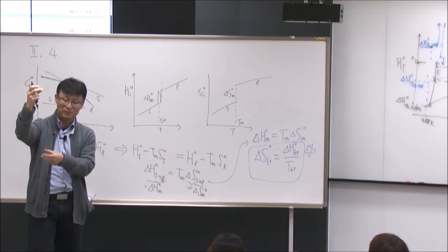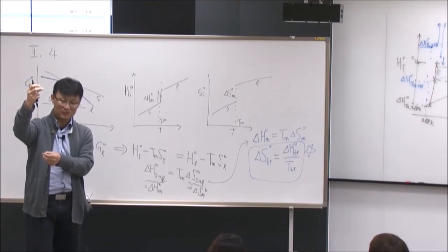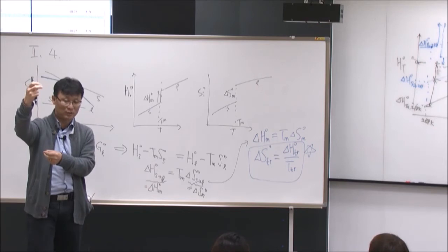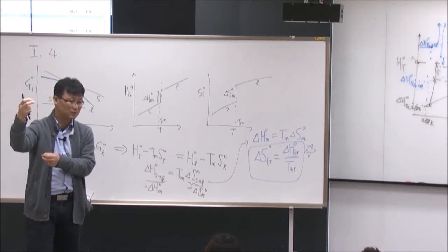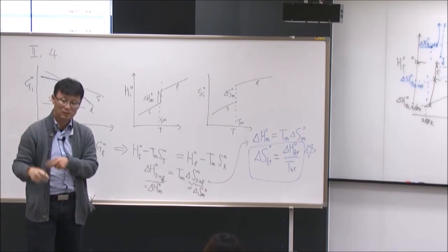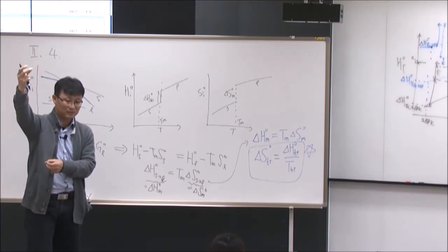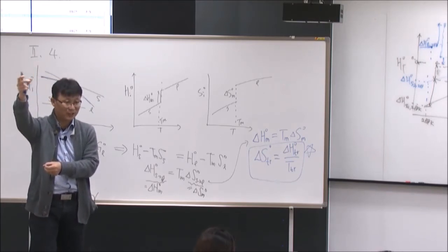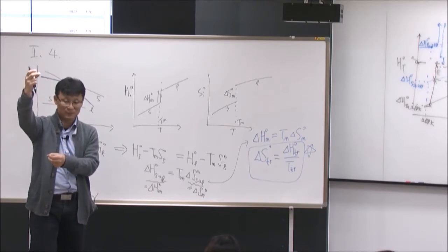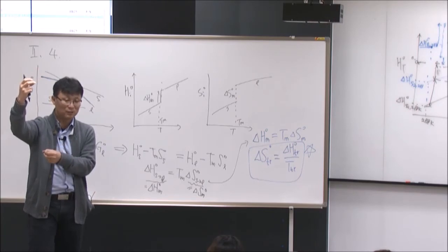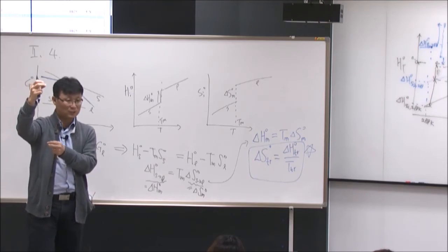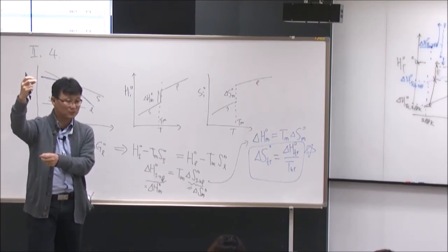So the entropy difference between FCC becoming the liquid phase should be some general value, regardless of the element or species. Same thing for the liquid becoming gas phase, regardless of whatever element you have. The structure change is almost the same, so there should be one general, reasonably similar value for the liquid becoming gas phase.